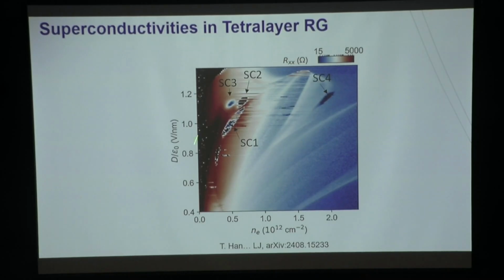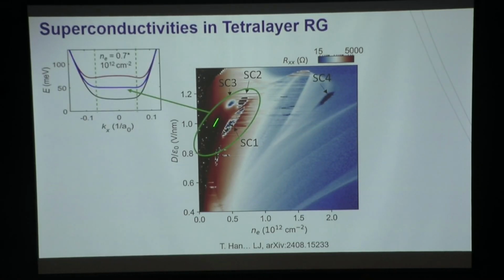As you can see, there are a lot of features on this map, but there are four regions that show RXX vanishing, which I call SC1, this big oval here, SC2, SC3, and SC4. For every one of them, we have checked that the resistance does go to zero. We checked the nonlinear IV. We checked their BKT transitions. We're pretty confident they are all superconducting. Especially these three here correspond to when we open up the band gap to generate a very flat bottom of the conduction band. And we put charges into that flat part, okay? Again, there's no Moiré effect. There's no TMD or SOC. This is just what pure carbon does.